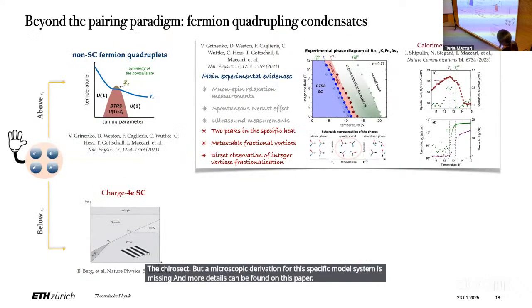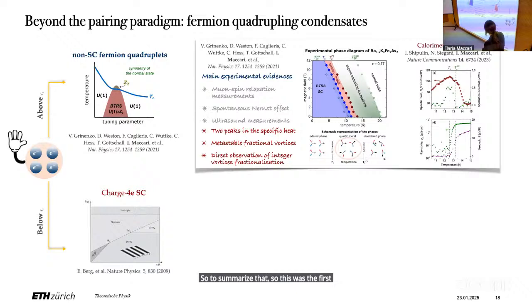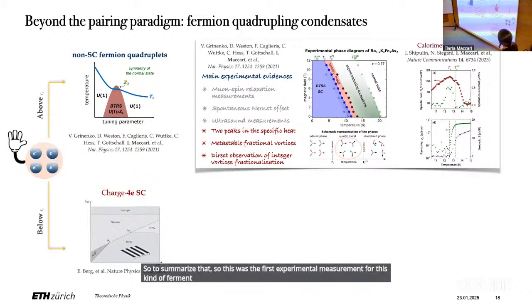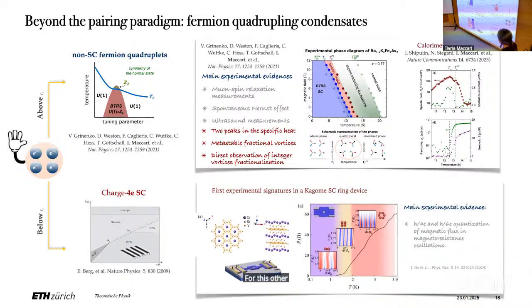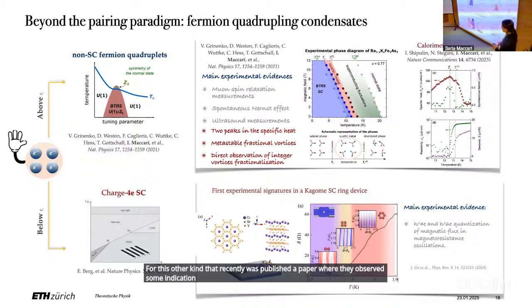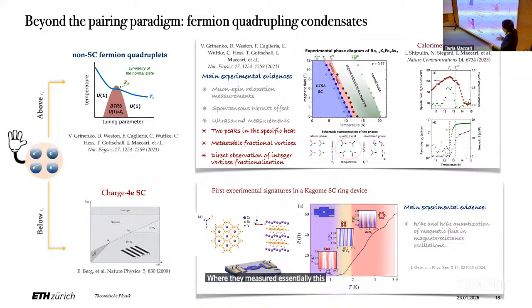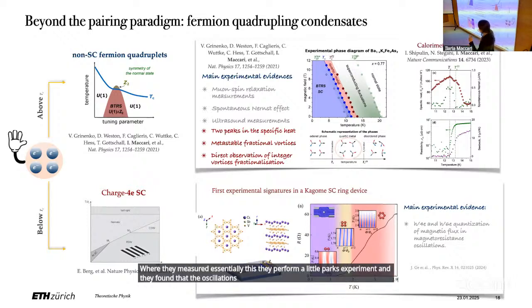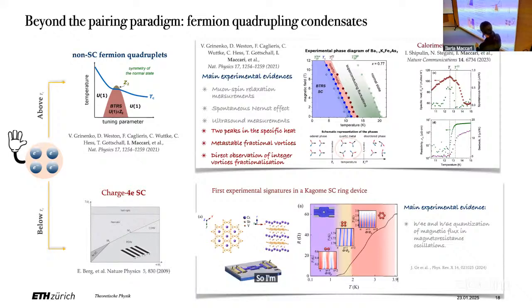So to summarize, this was the first experimental measurement for this kind of fermion quadrupling condensate. For this other kind, recently a paper was published where they observed some indication for this phase in this Kagome material, where they performed a Little-Parks experiment, and they found that the oscillations changed from being h over 2e to h over 4e and 6e, suggesting even the presence of a sextuplet condensate. But these experiments still need to be verified carefully, so I'm just reporting it now.